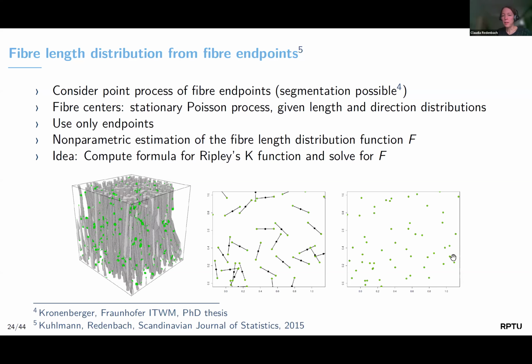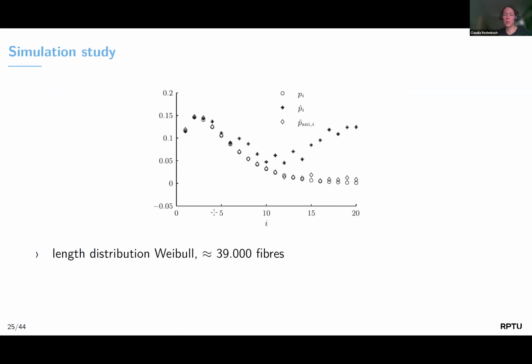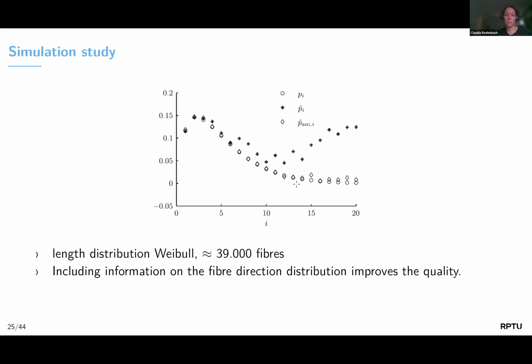It's kind of surprising that just from such a pattern where no fiber information is left, you could still see the length distribution. But in a simulation study, we could show that actually for a large number of fibers, it worked well. So here in circles, you see the actual distribution. So now we get a non-parametric estimate, so basically a histogram. The initial estimate is here the little stars. This can be improved if we take into account the direction distribution of the fibers.